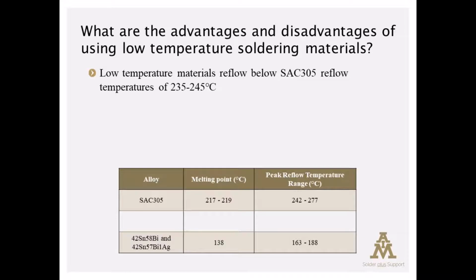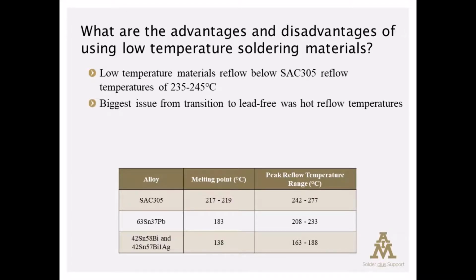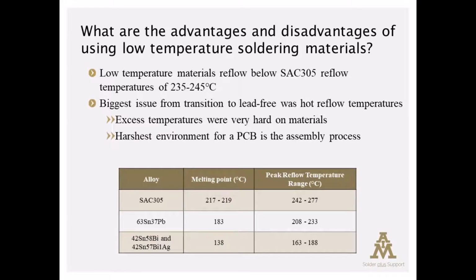That's quite hot, and it was one of the biggest issues in transitioning from a leaded tin lead system, which had peak reflow temperature requirements under 220 C, to this 240 to 245 C required peak temperature. Plastics deformed, laminates delaminated, and the excess temperature just was very hard on the materials. I've heard it said that the harshest environment any circuit board withstands is the assembly process. And I think that's a great thing to keep in mind.